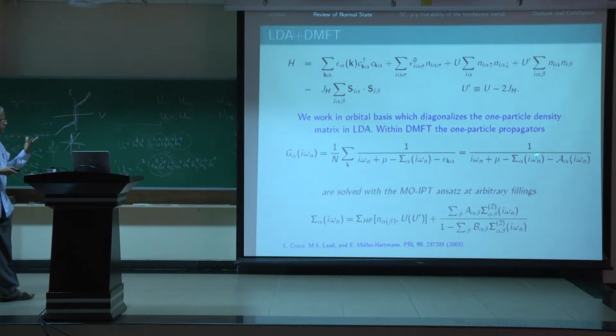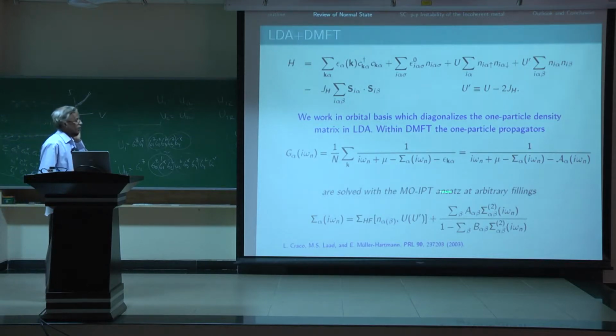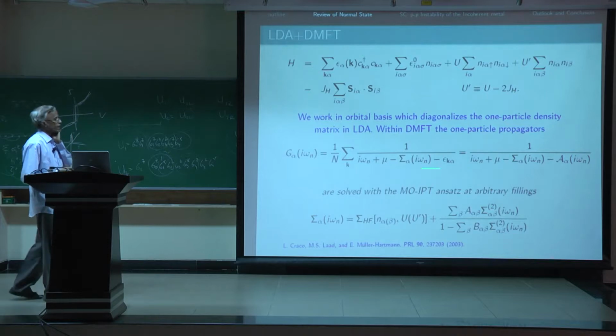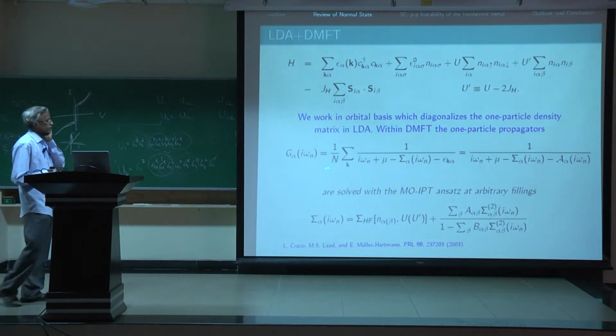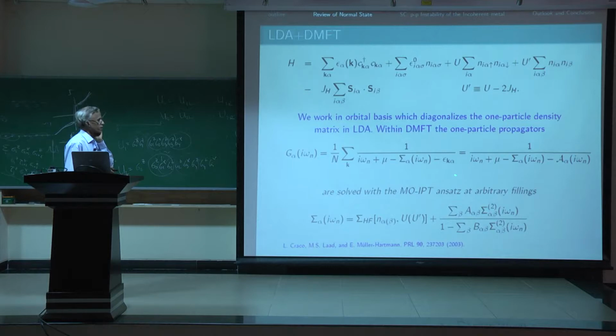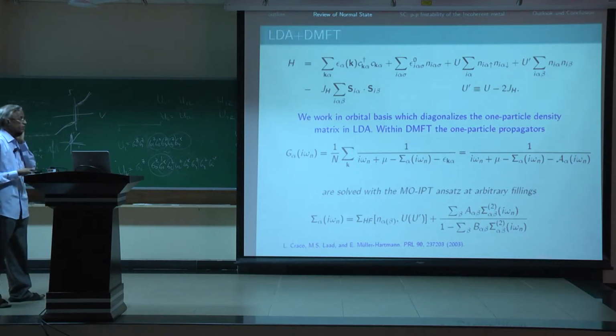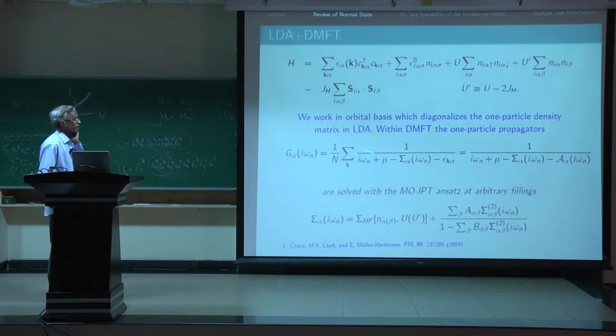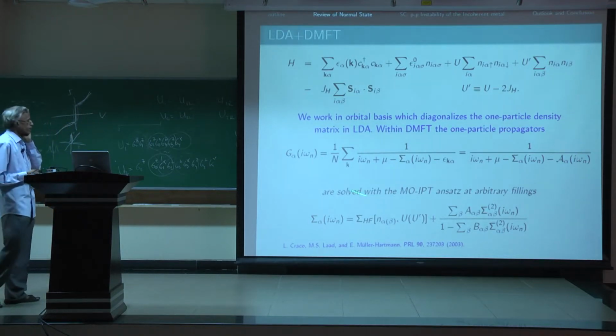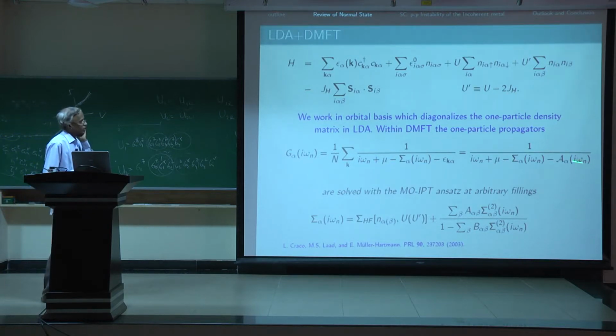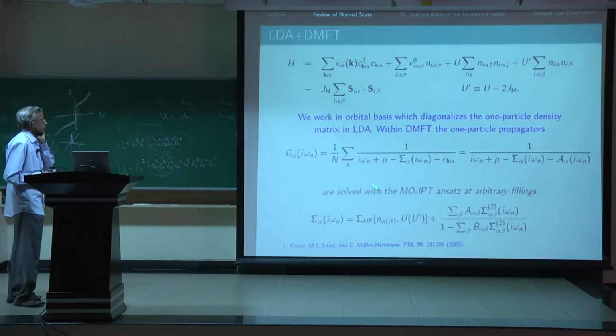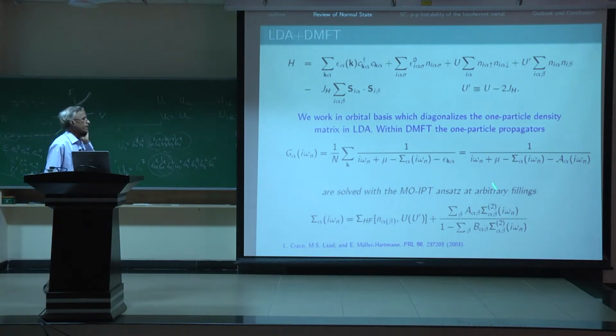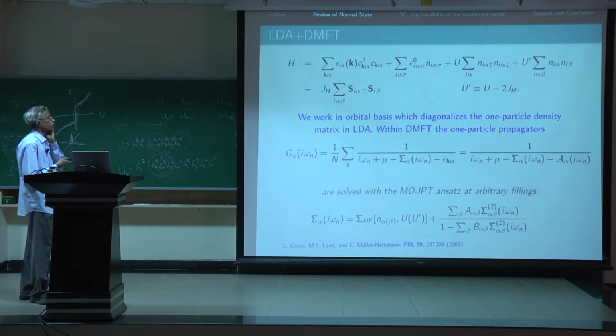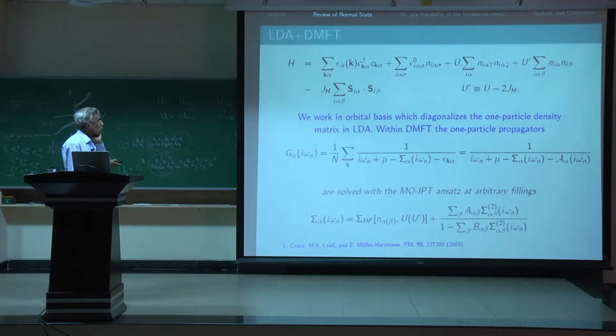So in view of the advantages which a diagrammatic solver like this presents, so one can calculate all response functions at arbitrary temperatures for arbitrary filling. There are no difficulties associated with analytically continuing Matsubara frequencies onto the real axis and so on. So, taking that kind of constraint in view, we adopted the simplest solver like MOIPT, but there are other solvers like NCA and so on, which could also be used for multi-orbital situation like this, though we have not done that.